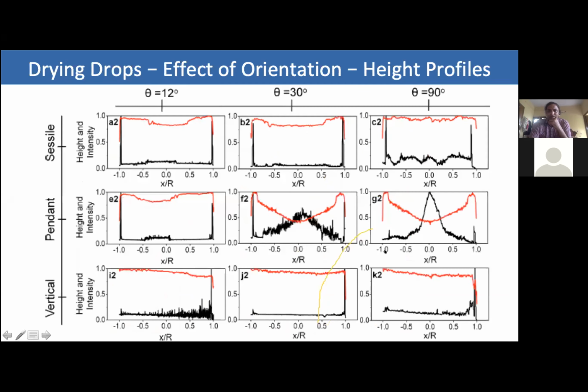So we have done experiments to quantify the spatial distribution of particles in the deposit. This is the intensity profile, which shows that there's more deposition of particles in the center in the case of pendant drops, and the intensity of that deposit increases with increase in the wettability. However, in the sessile drop, the peaks in this black curve show that there's a coffee ring formation because of the accumulation of more particles at the edge, irrespective of the substrate wettability.